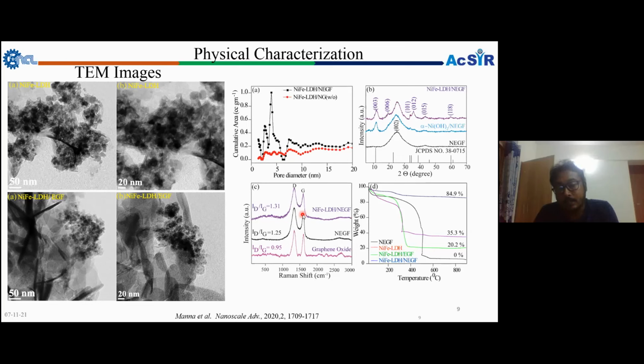The graphitic structure is needed for better durability. Second thing, as we already told, is the importance of the nitrogen and the metal particle anchoring. And the second thing is that we have checked the TGA, the thermal gravimetric analysis, to find out the catalyst loading, because the active center is the nickel iron layer double hydroxide, and this is the support.